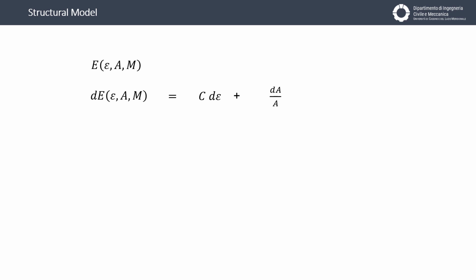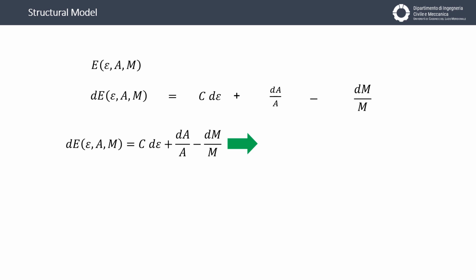It's the model that we can see in the literature. But in this case, we use the contribution of the austenite in this manner: the variation of austenite on the quantity of the austenite, plus the contribution of the martensite in the same manner but using a negative sign, because we postulated that the austenite transforms into martensite and vice versa without any other intermediate phases. The equilibrium takes place when this differential is equal to 0, like this.